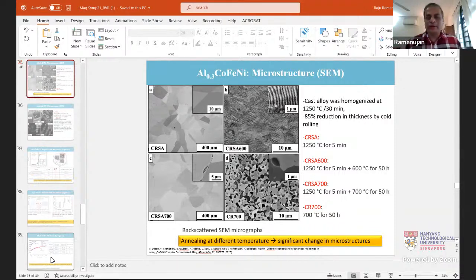Yeah, so that's good. In this LENS technique, each layer thickness is really quite small, because the powder is impinging on a substrate, and then the laser hits it. So you can get a very fine gradation in the properties using the LENS technique. In the other two techniques, the composition gradient that you can produce depends, first of all, on the powder size, but one issue is that there could be interdiffusion between different layers. If you really want discrete layers, you need to put some kind of inert foil, like tantalum foil, to prevent this interdiffusion. In some other cases, it may not matter. A continuous distribution may be what you really want. So it depends on your application. But I personally don't think it's a serious limitation from an engineering perspective.